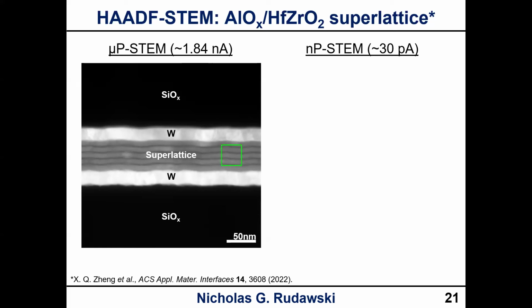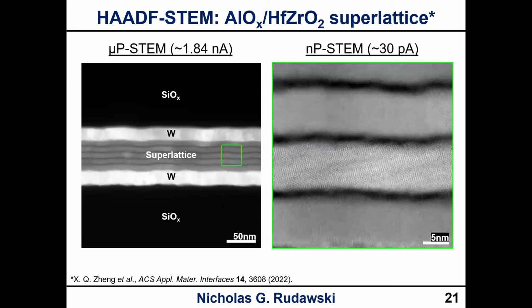Okay, so if we switch our instrument to nanoprobe and we mag in really closely on the superlattice structure, this is a really nice HAADF STEM image of one of these layers. Okay, so you can actually see in the third layer some really nice atomic level detail. So this was actually an instance where I very meticulously and painstakingly aligned that layer to the zone axis that it was in. Okay, those layers are about